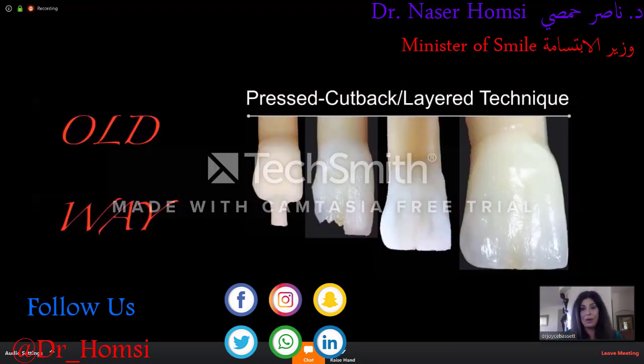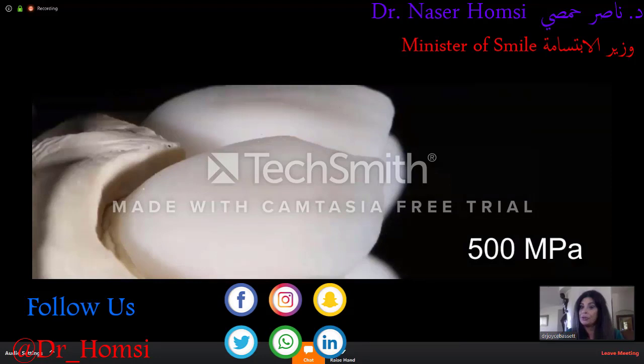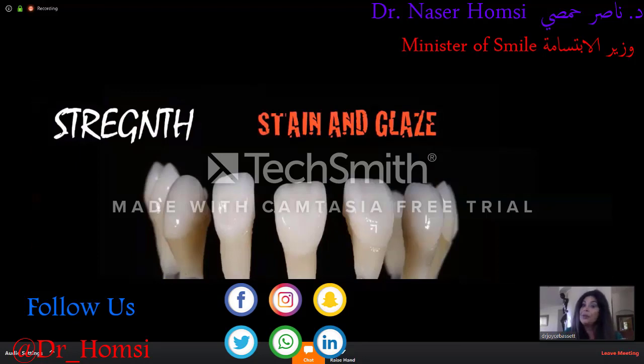The old-fashioned way was to cut back and then put the feldspathic everywhere. The new way that we're doing, because we want 500 megapascals of strength on the incisal edge, that's where the load is. And so now we're layering only the facial and leaving that area there for strength. Because if you really want strength, you just want to stain and glaze and do everything on the top and try not to layer it off.